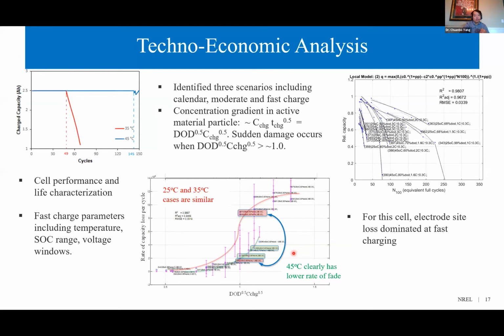Model regression indicates capacity fade in fast charging cycles is likely caused by electrode site loss. At moderate cycling, capacity fade was mainly due to lithium inventory loss.